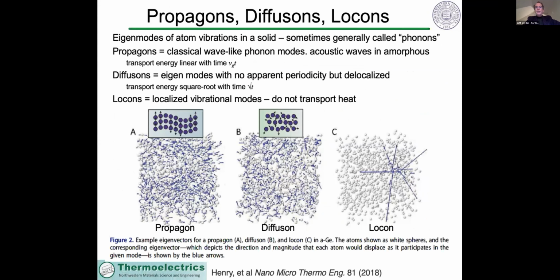So one of the things that we've been thinking a lot about recently is this idea that the thermal transport is not simply by classical phonons, but we should think of them as being separated into propagons, diffusons, and locons, according to the nomenclature of Allen and Feldman. So a propagon is a wave-like lattice mode that looks like a traditional phonon, and a locon is a localized atomic vibration, thinking about a local, maybe Einstein type mode. Much of the heat in complex materials is transported by diffusons, which are much larger than a locon, but have an eigenstate which looks very different from a traditional wave. It's very diffusely